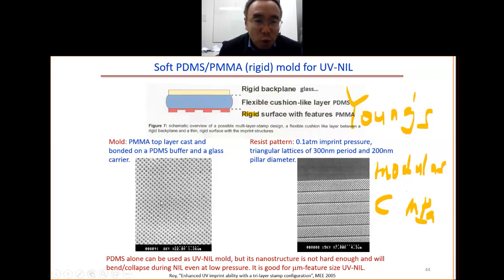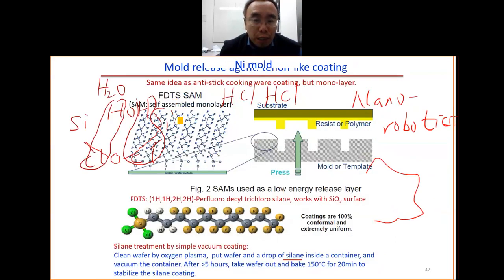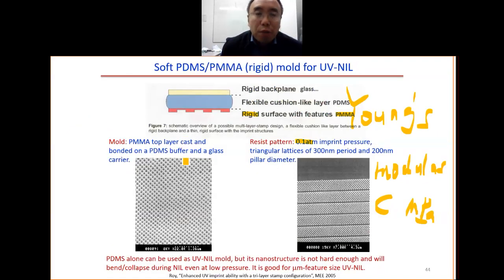But here you can see you have this mold. After imprint, you get the pattern into the resist. Here it's done by using UV imprint at very low pressure. But the problem is that PMMA is not compatible with this process. You cannot make the surface low surface energy. As a result, maybe after one imprint or maybe two imprints, there will be lots of peeling off of the mold. It's only good for maybe one or two imprints. Then there will be a peeling off problem because this one cannot be made a low surface energy.